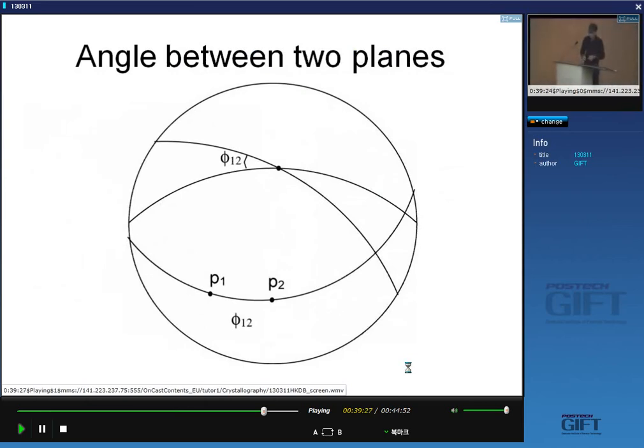The angle between two planes we've already determined by putting a great circle on it and measuring it, reading it off. And of course that's the same as the angle between the traces of those two planes, because the trace is simply at 90 degrees to the pole.